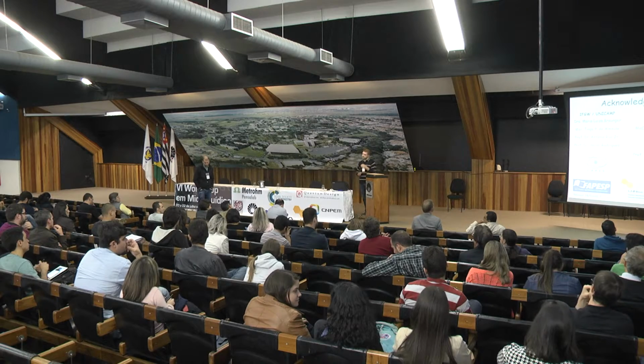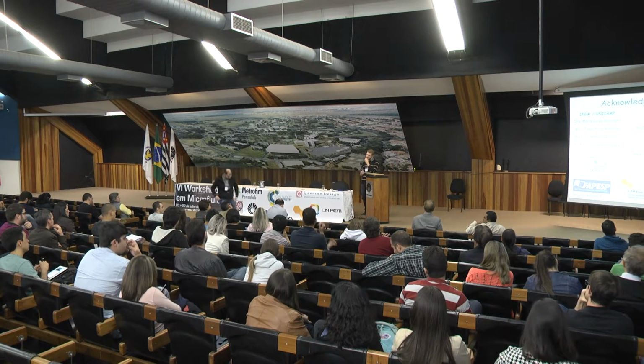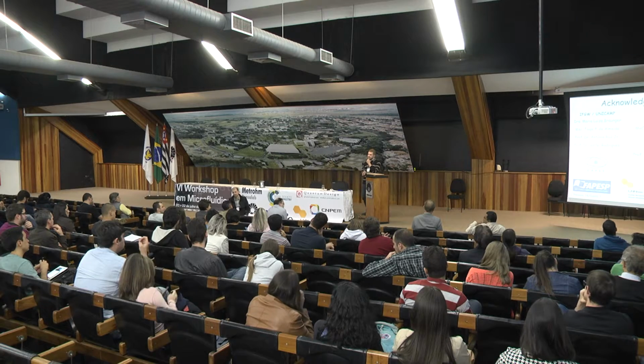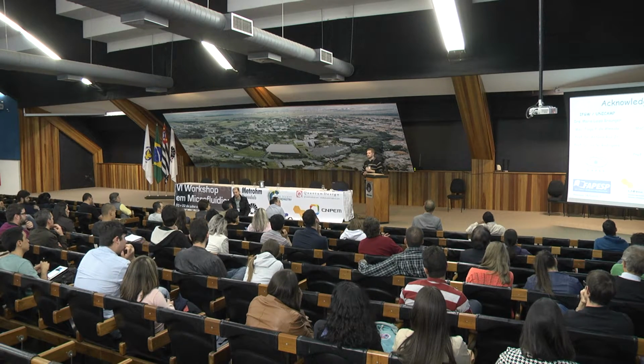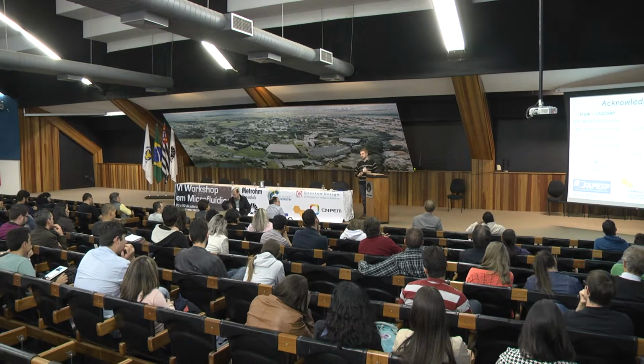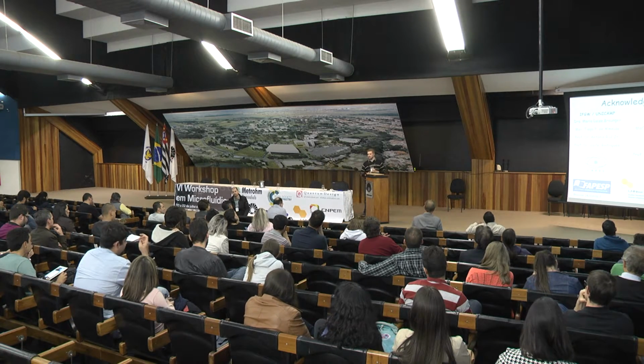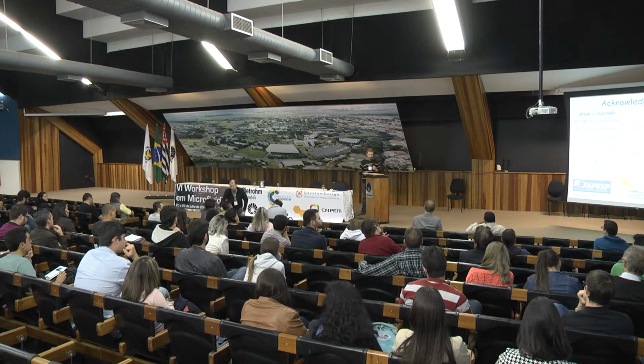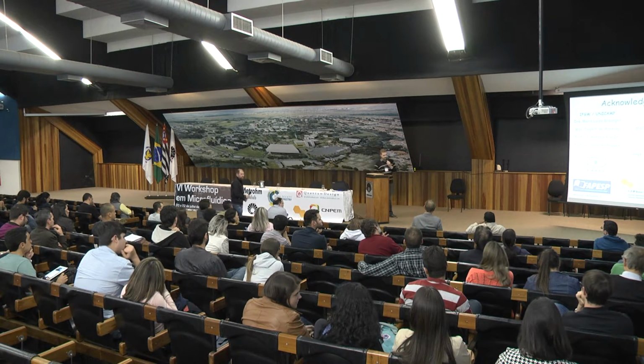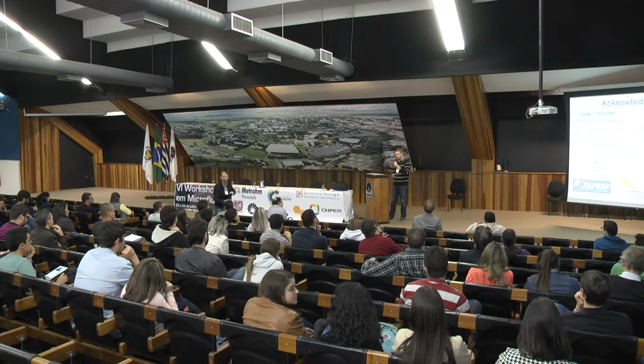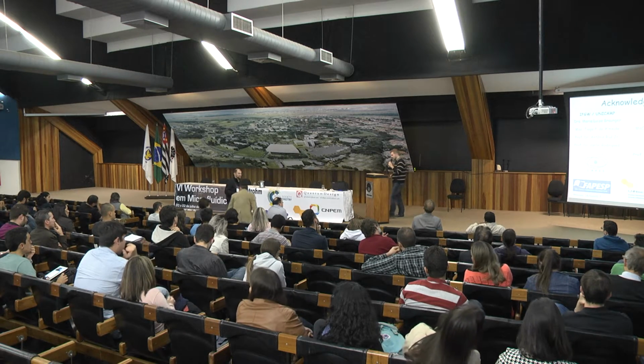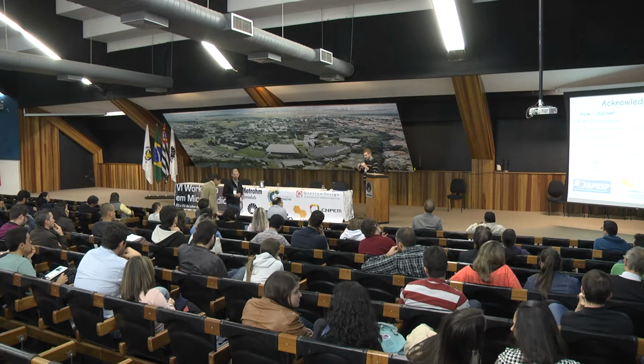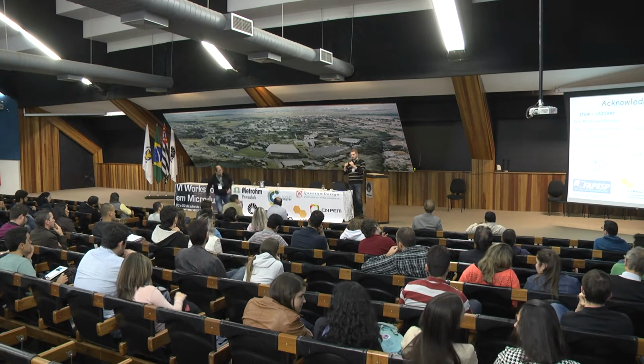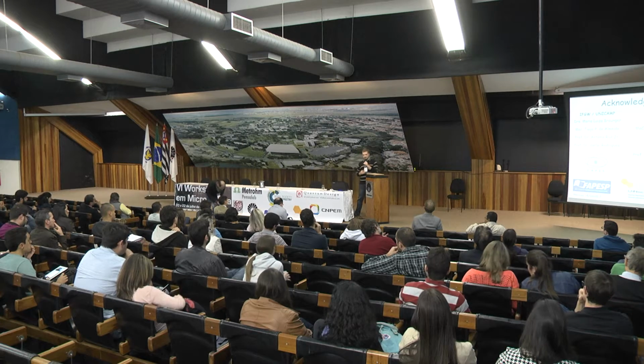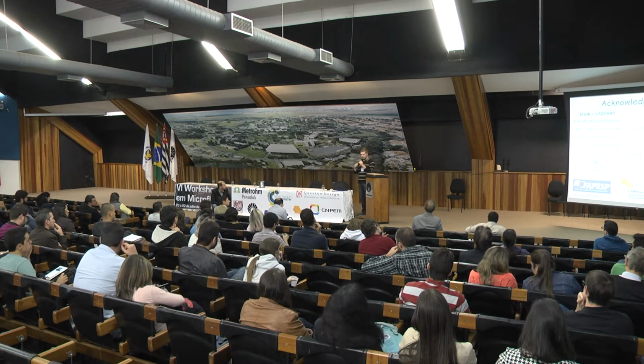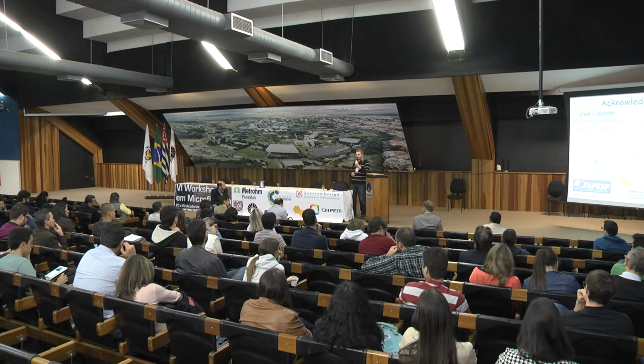I would like, if it's possible, to talk a little about the mechanical properties of this 3D printed carbon electrode, if they are good, if you have issues with exfoliation or adhesion of these electrodes with the other parts of your device. We didn't perform quantitative mechanical experiments on these 3D electrodes, but since they are the same material as the substrate, the polylactic acid, we don't expect to have any kind of delamination of the electrode.